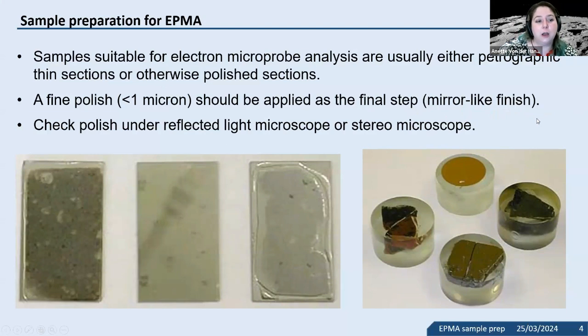And if that is achieved, you can check your polish under a reflected light microscope or even under a stereo microscope, where I just angle the surface so that, again, it reflects back. And that is oftentimes already a good indication. If it's not good enough in this view, for sure you will run into problems during analysis. And then, of course, if you can, just looking at it in an SEM or something might be helpful, but usually just a reflected light microscope is a good enough step to do that.